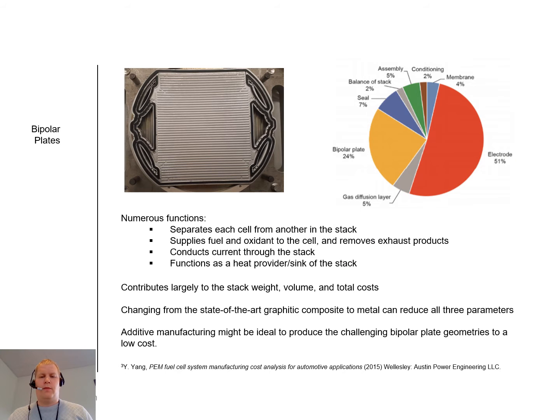Bipolar plates have numerous functions in a fuel cell stack. They separate each cell from another in the stack, as you could see on the previous slide. They supply fuel and oxygen to the cell and remove exhaust products using the flow channels. They conduct current through the stack, and they function as heat provider and heat sink of the stack, normally using a liquid coolant that passes through internal flow channels of the bipolar plates. The bipolar plates contribute largely to the total stack weight, volume and total costs. And as you can see here, for an 80 kilowatt PEM fuel cell stack calculation, almost a quarter of the total costs are due to bipolar plates.